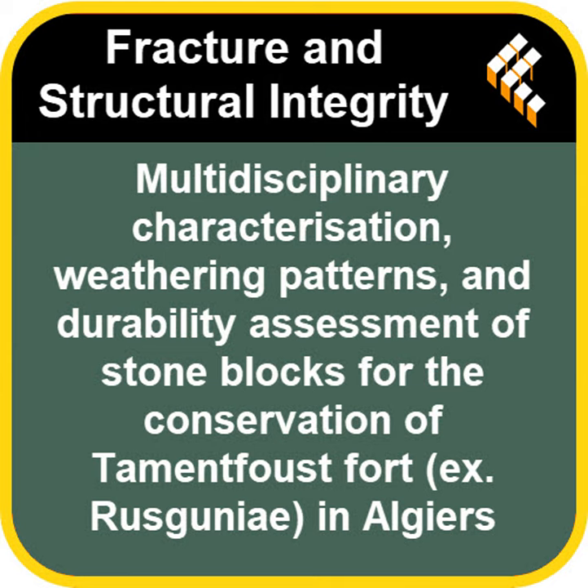Okay, what about the acid? Is this modern pollution hitting an ancient structure? That's exactly it. They tested the denser T2 limestone with hydrochloric acid, and the results: a 35% drop in compressive strength. 35%, that's huge. Massive. It went from 27.57 MPa down to 17.94. Now, it didn't lose much mass, only 1.64%, but that loss of strength is a huge red flag for the fort's structural integrity long term. Yeah, absolutely.